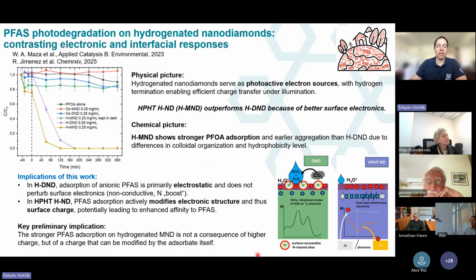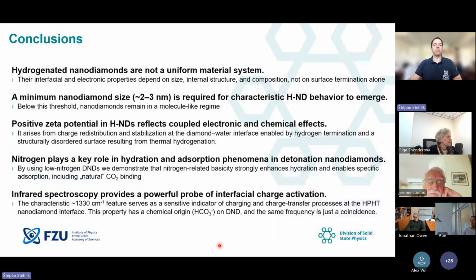So that's our idea, and it brings me to the conclusion, where I wanted to introduce the hydrogenated nanodiamonds as a non-uniform material system with interfacial and electronic properties depending on the size, internal structure, and the composition. We saw that a minimum size of 2-3 nanometers is needed to obtain this characteristic hydrogenated nanodiamond behavior, like this positive zeta potential and colloidal stability.